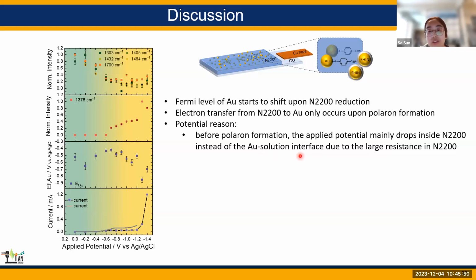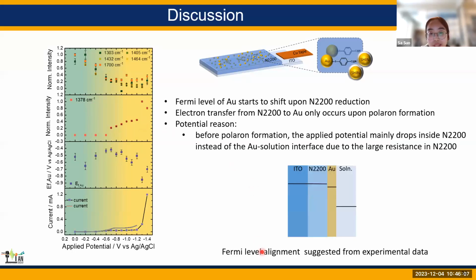So basically there is a large area of electron transfer from N2200 to gold because of the large resistance. And from the observation of the Fermi level relation with the polaron formation, we can see that if we just plot the Fermi level alignment among these four configurations,